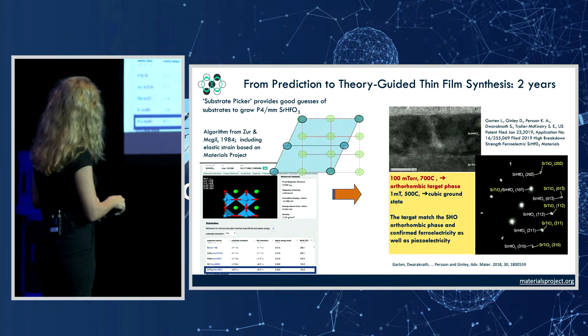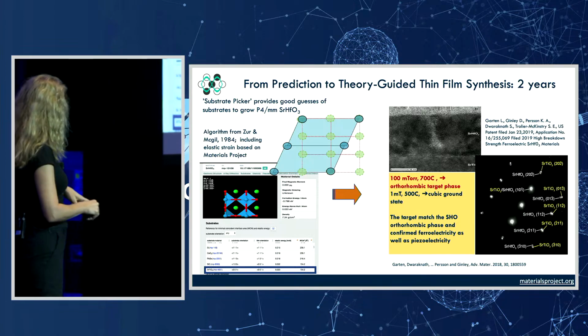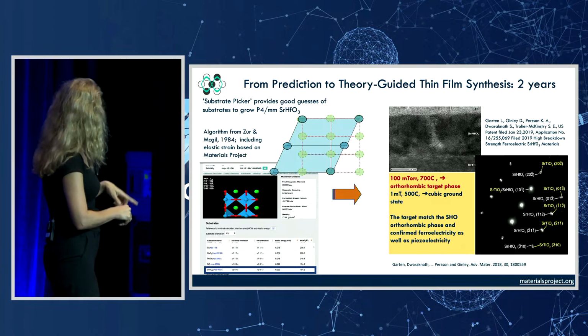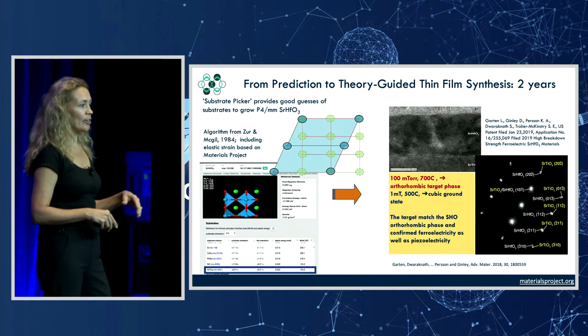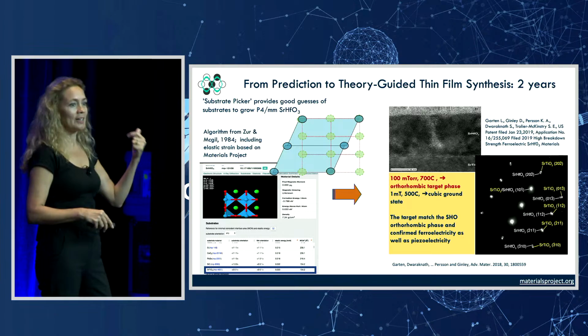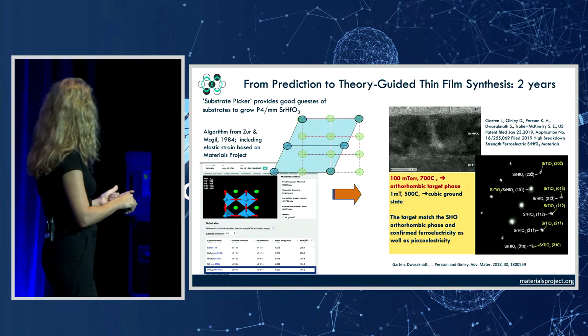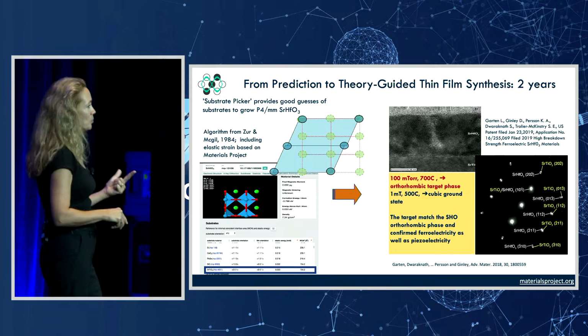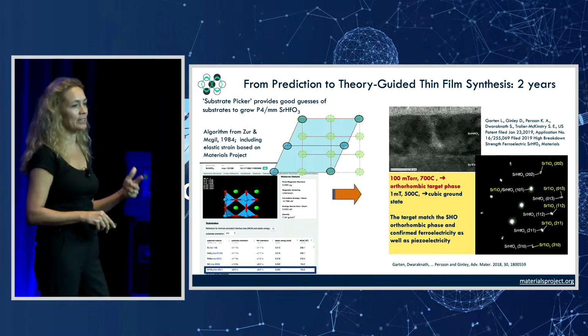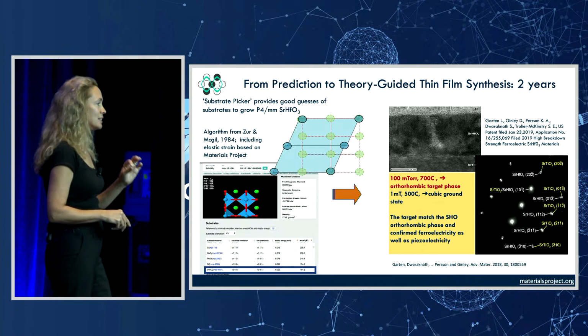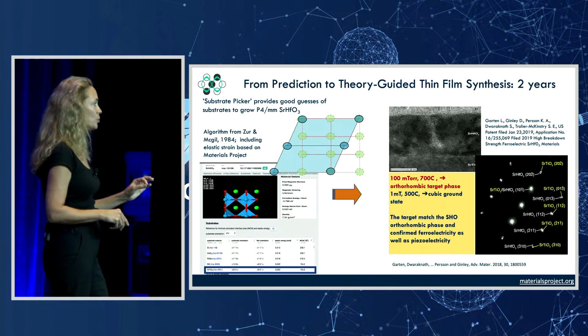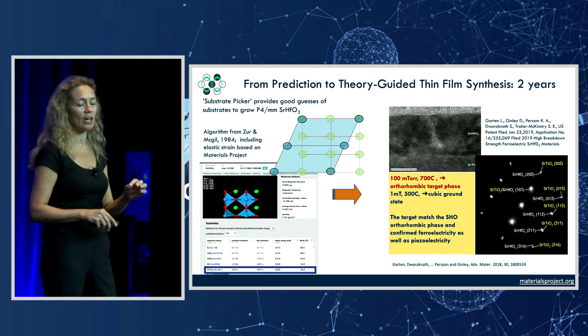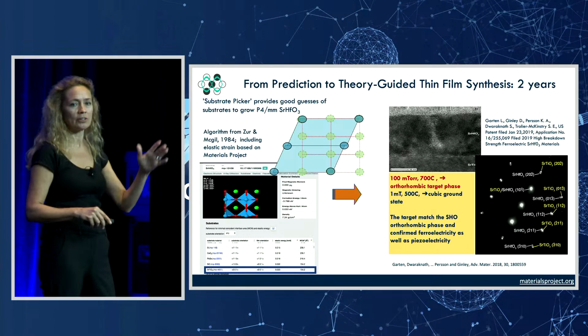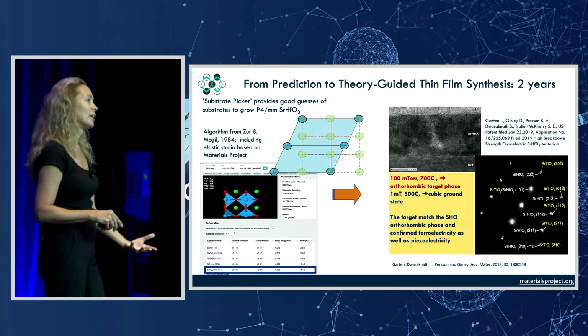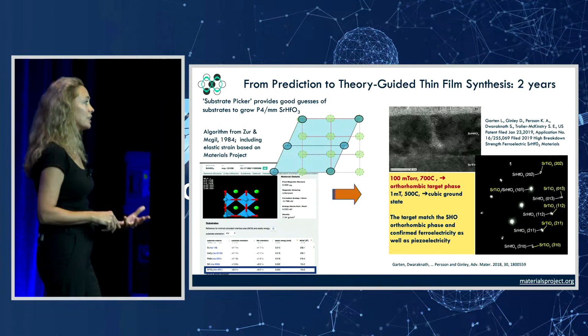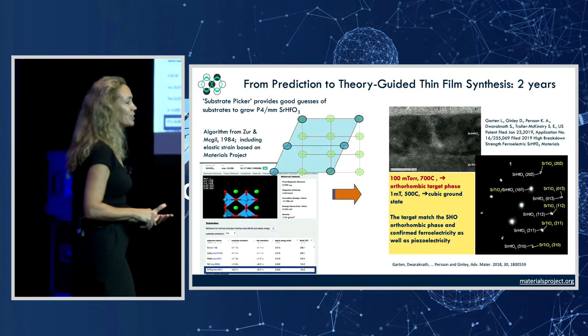We made a particular one. It was a niobium-doped strontium titanate substrate. And after 2 years of making the substrate, different kinds of synthesis conditions, Lauren Garton was able to make this material, go to SLAC and characterize it and show definitively that, yes, indeed, this very thin film is that particular strontium hafnium oxide and not any of the other more low-lying, more stable versions of it, which was a hero attempt, in my opinion. 2 years.